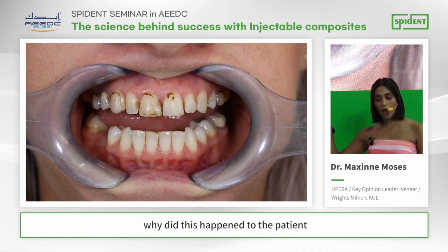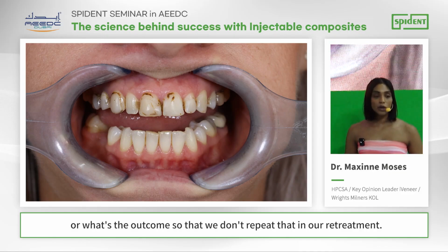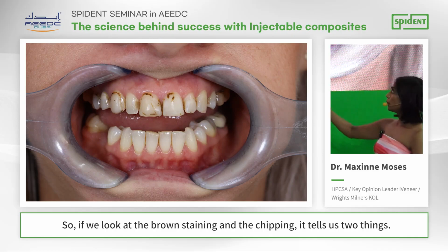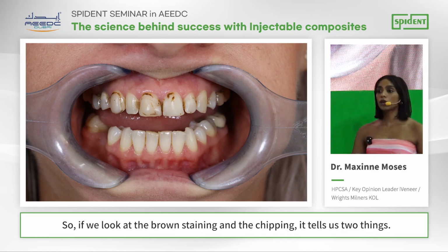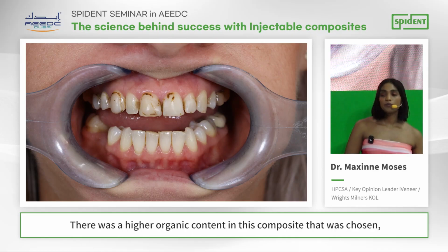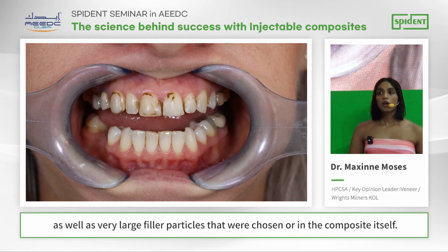Why did this happen to the patient, so that we don't repeat that in our retreatment. If we look at the brown staining and the chipping, it tells us two things. There was a higher organic content in the composite that was chosen, as well as very large filler particles.